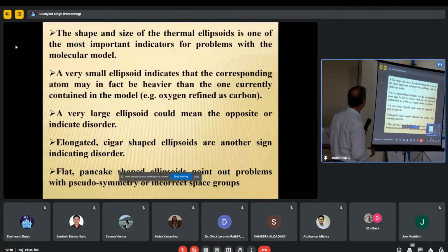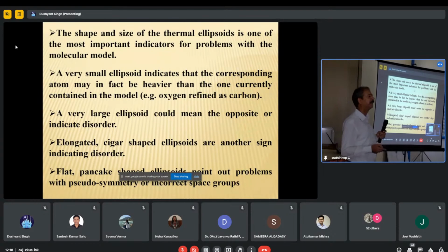Flat, oddly shaped molecules show either pseudo-symmetry or an incorrect space group. Suppose your space group is P21/a and you are giving it P21/c. There is hardly a difference, just 1/4 along one of the axes. So you should have clear knowledge whether the space group is P21/a or P21/c. Otherwise, from the symmetry point of view, the difference is very, very small. When you plot the equivalent diagram of a space group, you will hardly notice any change. But when you refine P21/n as P21/a, then all these problems will come.